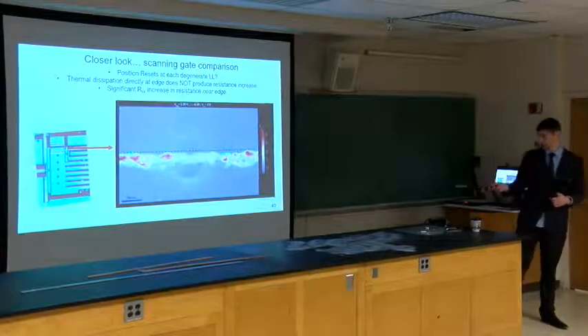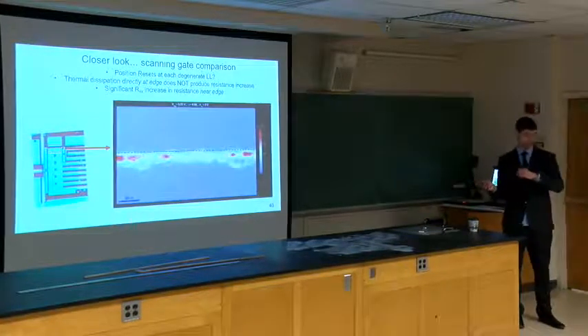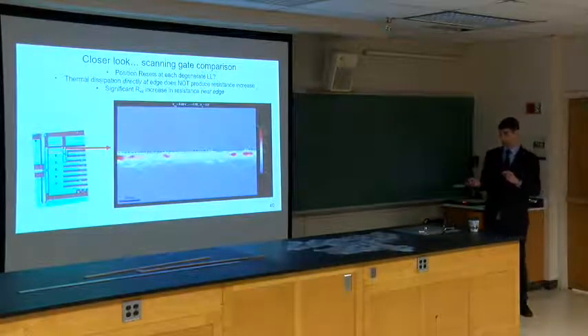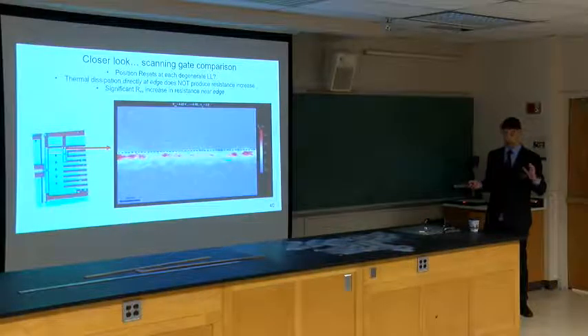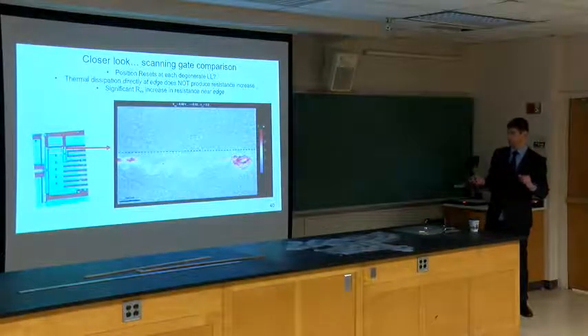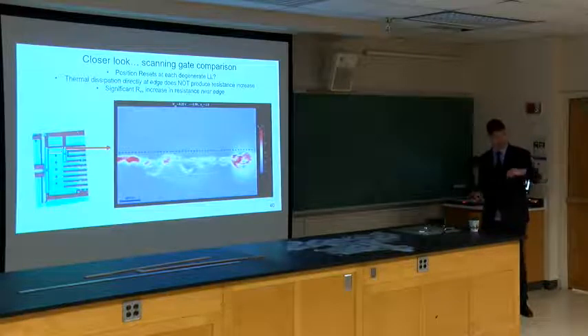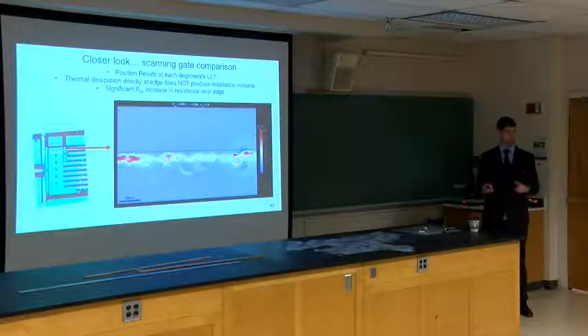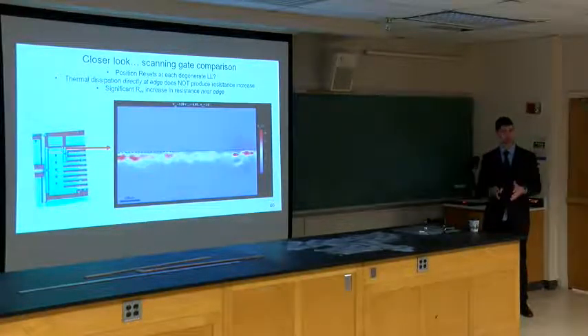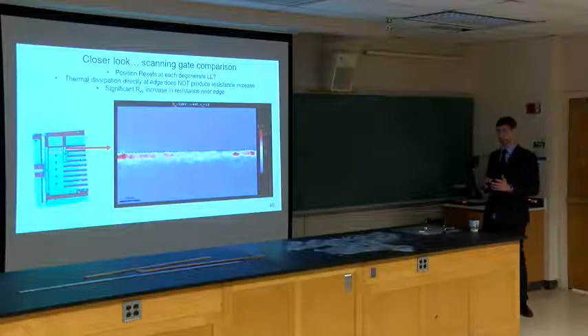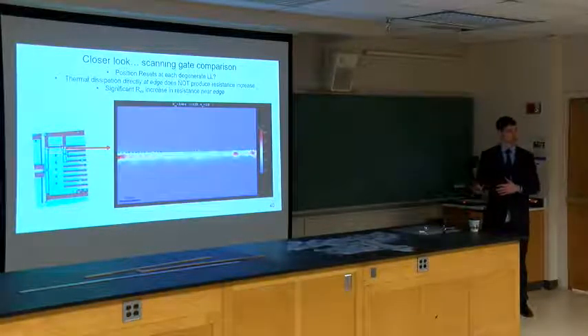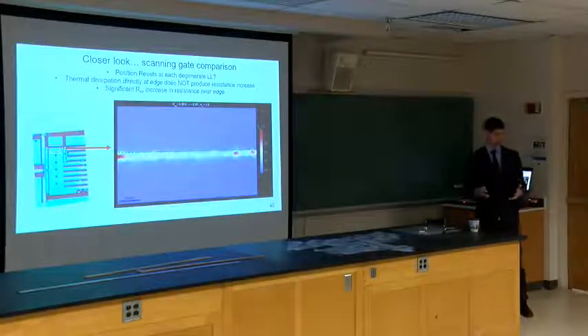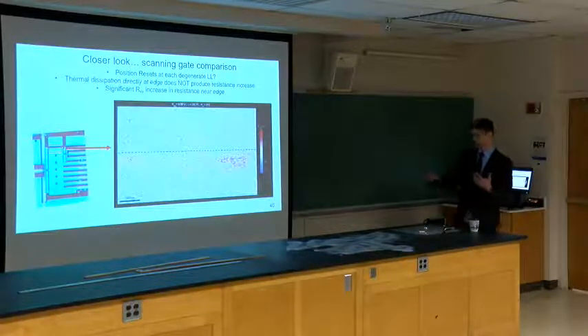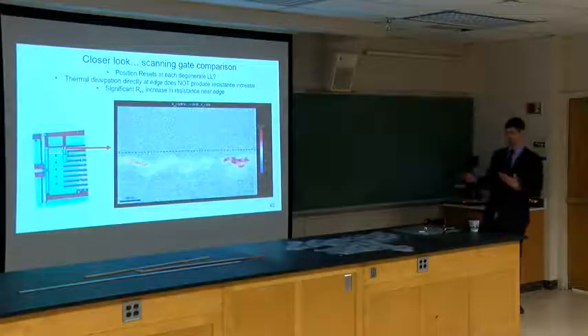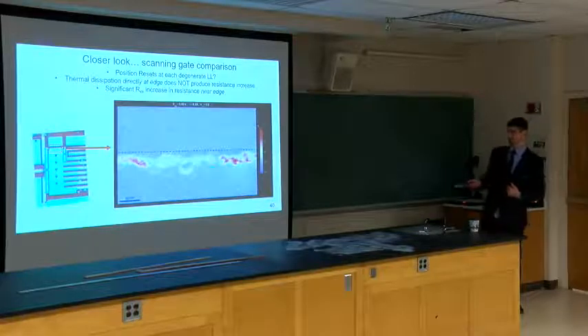In the previous slide, the dotted line here matches actually the physical edge of the sample, where in the previous slide there were the rings that were showing up. Now, if we look at where the resistance is changing as the tip is crossing, they're in two different places. So where we see dissipation from the IV characteristics is not where we're seeing heat generation, actually, which is interesting. So there has to be two distinct mechanisms that are going on here.